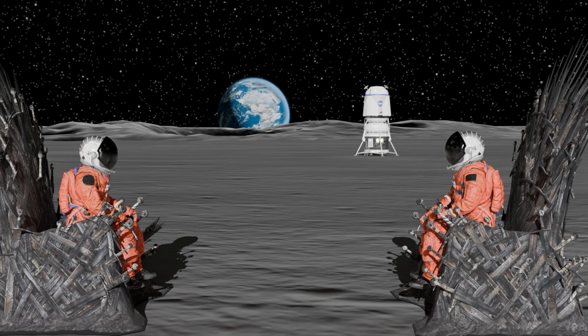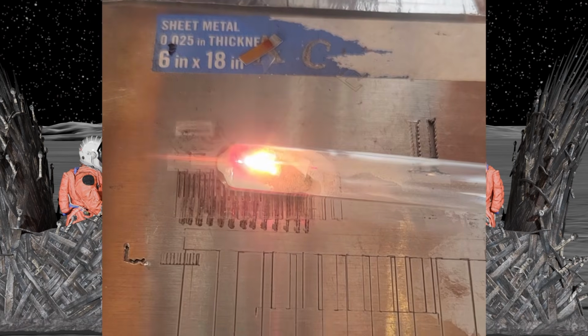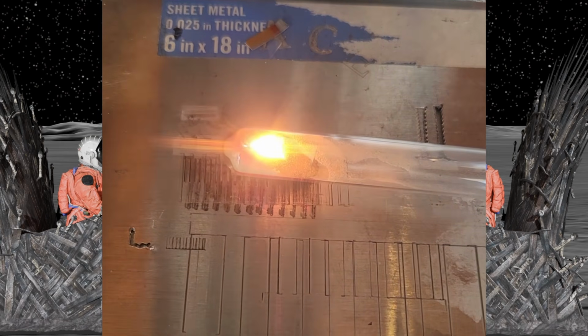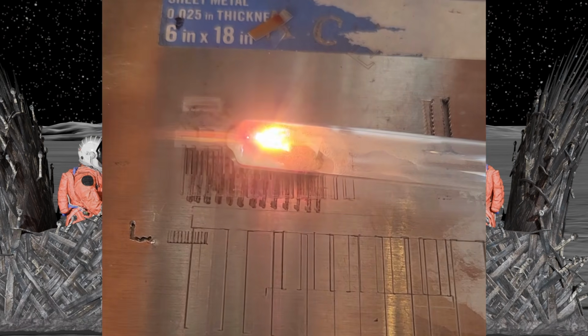Yeah, what we found is that basalt and iron are kind of poisons to the process. Having beneficiated the process and removing the iron absolutely makes things a lot easier. You can do iron by itself as well and be really successful with it. But when it's mixed with the other regolith, it's a very potent, almost poison. If you think about it, it's going to absorb a lot of the energy that you're trying to put in other places. Now, you can use that to your advantage if you have something that is very white, for instance, like titanium dioxide, and you start with some iron monoxide as a nucleation seed where you create the heat in that substrate, and then the heat creates a phase change in the material around it, and that phase change causes the metal to absorb light differently.